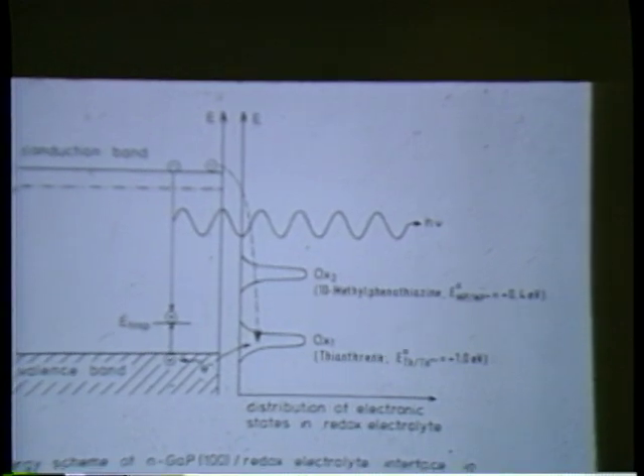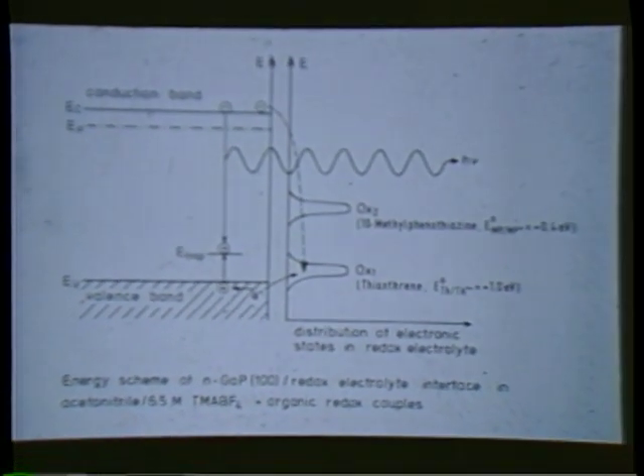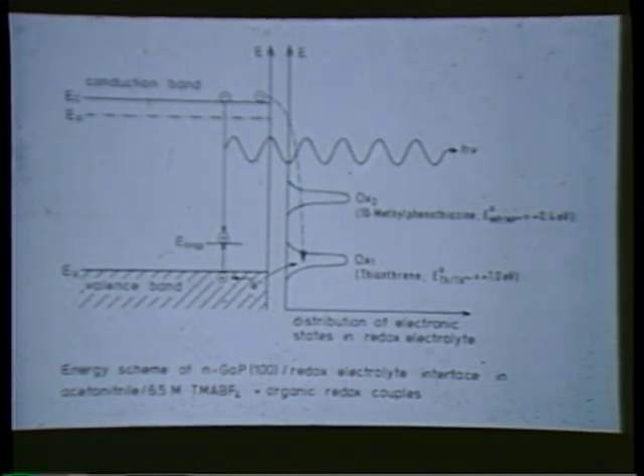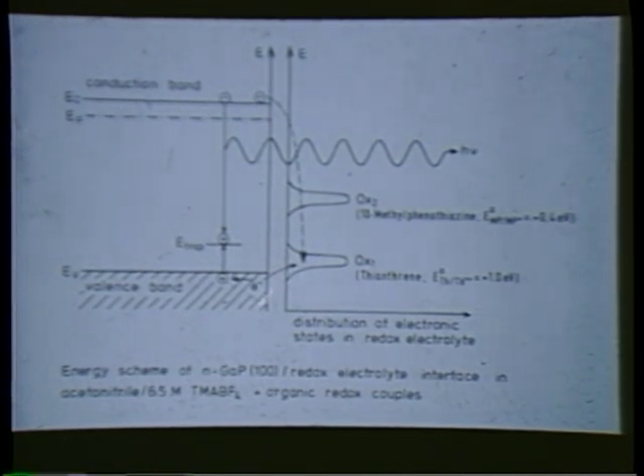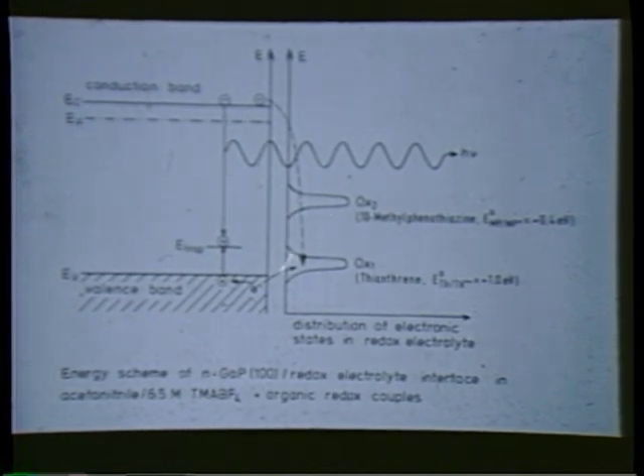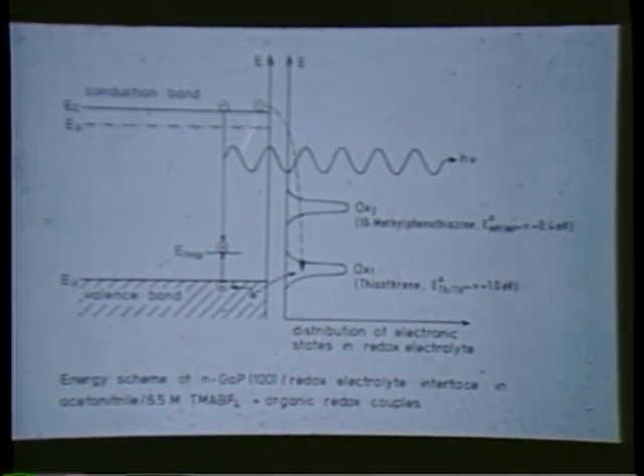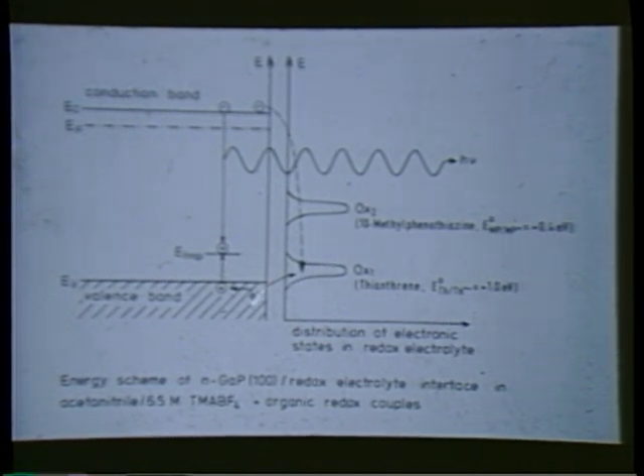Now, what does this mean? One can derive a correlation between the energy levels in the electrolyte and the semiconductor, which are shown here. Namely, that the one system can easily inject holes, but the other cannot. And that means if we have enough electrons, in the case of the second system, the injected holes react with the electrons, they recombine. At first, it occurs as radiationless recombination via surface states, surface recombination. That you cannot see. But if holes can escape into the bulk, we see luminescence from the bulk.